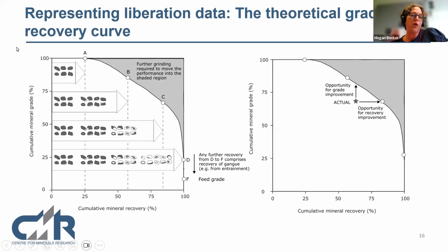On the Y axis I've got cumulative mineral grade, and on the X axis I've got cumulative mineral recovery. My first data point is obviously a dummy data point up at 0% recovery. I will recover only the fully liberated material. So the dark is the valuable mineral, and that will get me to point A, and the grade at point A is going to be 100% because I'm only recovering fully liberated particles. Then I start recovering what I would call high-grade middlings. So now I can accumulate the recovery of the fully liberated material and the high-grade middlings, and it gets me to 50-something% recovery. And obviously, we recalculate the grade, and it's coming down.